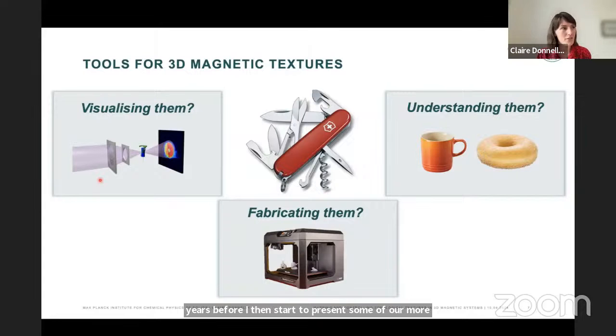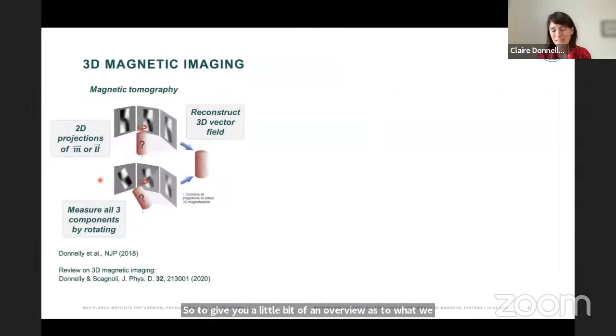So to give you a little bit of an overview as to what we have available to us at this point in time with three-dimensional magnetic imaging, essentially for 3D imaging of magnetic configurations, we use a tomographic technique. The idea is that you can measure two-dimensional images in transmission of your configuration. You then measure multiple sets of these projections for many different orientations of your sample with respect to your probe. And then you need reconstruction algorithms, which we've developed and other groups have also developed, in order to reconstruct a three-dimensional vector field.